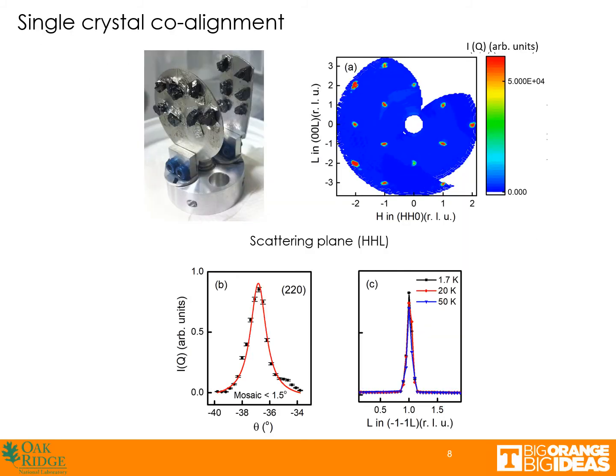Once we have some ideas about the spin excitation spectrum from powder average data, I co-aligned a number of single crystals with total mass around 1.2 gram along the scattering plane HHL, and the co-alignment is pretty good, with the crystal mosaic less than 1.5 degrees. And the last figure in this slide shows the temperature dependence of intensity, indicating that there is some magnetic scattering below the magnetic ordering temperature, 13 Kelvin, showing higher intensity at 1.7 K compared to 20 K or 50 K data.